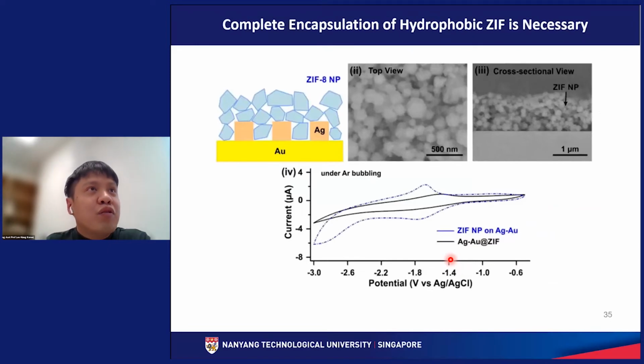So next, we also perform the same Raman, but right now, instead of using a thin film layer, we preform these ZIF-8 nanoparticles and deposit them onto our bimetallic catalyst. Over here, we can see that they are rather porous, right? So in another way, water can still penetrate through this thick layer over here to access the electrocatalyst at the bottom. That is why we are still able to observe the water electrolysis peak over here for this system.